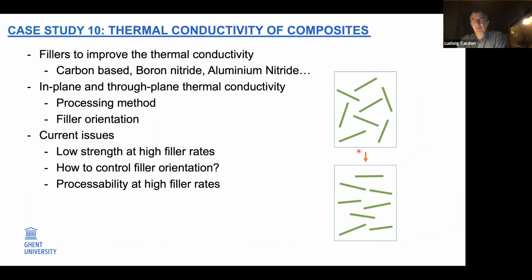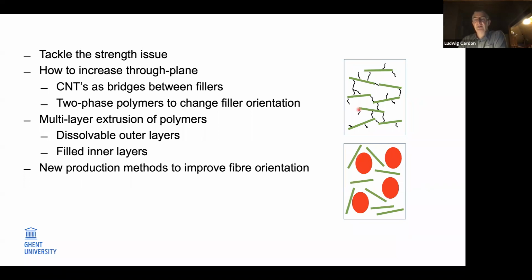So going back to the previous slide, when you are able inside your processing to reorient them randomly, like we did in our research, you create a kind of interconnective network so that the heat transfer in between your filler system is a lot better. To have an idea what we achieved up to now with these combinations, due to some confidentiality, I can't show the blends we use and the type of matrix material. But for instance, a normal blend of 0.2 could improve thermal behavior from 0.2 up to 1.5. So this is an increase of something like 6-7 times, which is very high for thermal conductivity of polymer materials. So I guess this is also the type of research which is interesting for Ghent University.